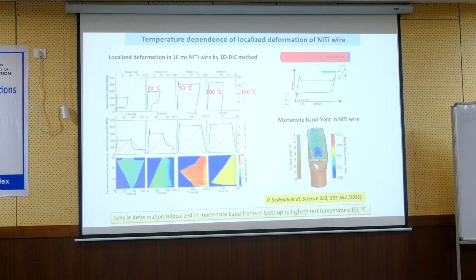so if I say we have the plateau, this actually means that the strain which is localized inside this propagating band is 16% long. But we don't know whether it is only transformation or some plastic strain. Yeah, so here it is mainly only transformation, but here it is partially plastic, and here it is mainly plastic. But still, without transformation, there would be no plateau. So it's not very clear what do we observe here. This is another method which we use to analyze this localized deformation.